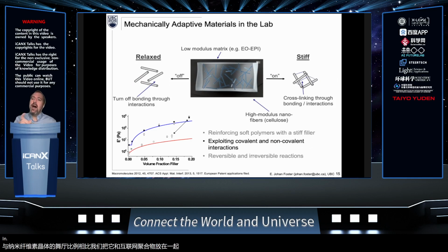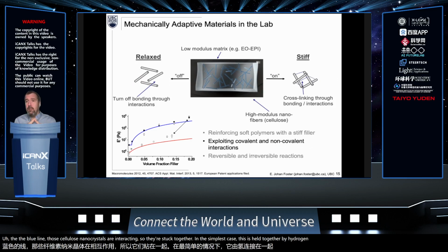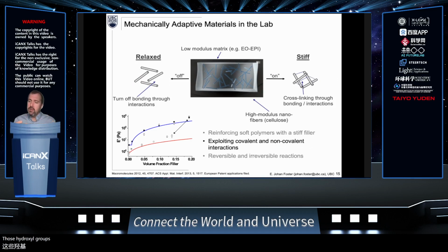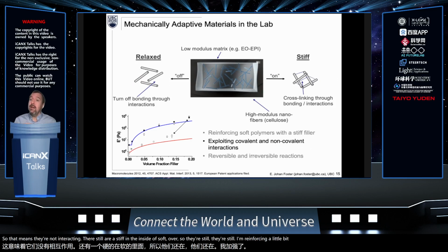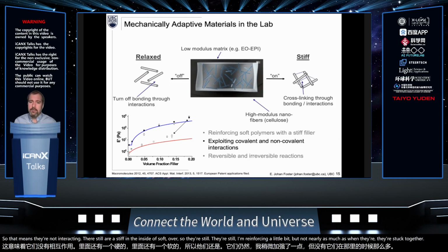Okay, in the top line, the blue line, those cellulose nanocrystals are interacting, so they're stuck together. In the simplest case, this is held together by hydrogen bonds. Those hydroxyl groups on the surface of the cellulose nanocrystals are interacting. Okay. Now, if we decouple those interactions, it becomes much softer. So that's down to the red case. Okay. So that means they're not interacting. They're still stiff, and they're inside of a soft polymer. So they're still reinforcing a little bit, but not nearly as much as when they're stuck together.